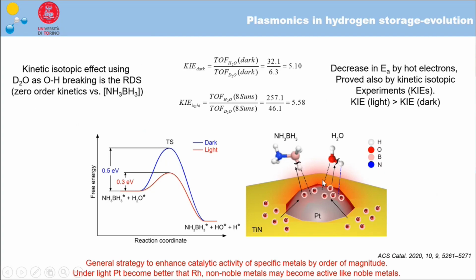And we also did some kinetic isotope effect experiments to go more into the mechanism, and what we discovered is that under light conditions, we are able to decrease the energy of the transition state by almost half of the initial energy under dark conditions. And so what we think is happening is that the hot carriers which we produce on the platinum surface are able to speed up the rate determining step, which is the rupture of the water molecules to start the hydrogen evolution with the ammonia borane molecules.